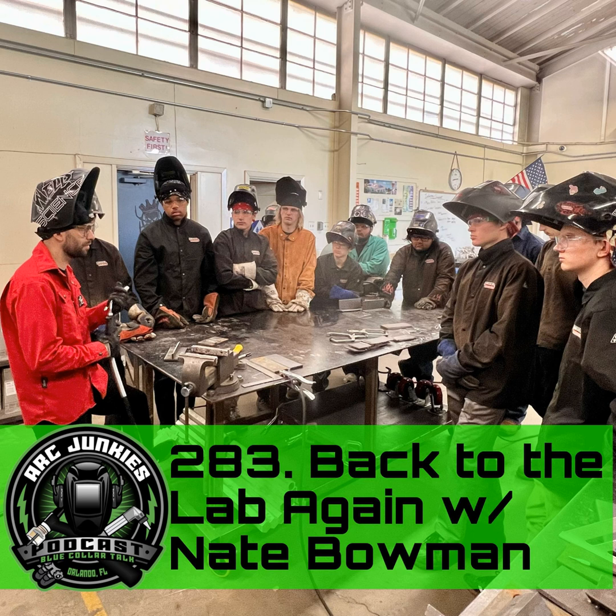But the problem with welding in AC is you don't get as much penetration as you do with DC reverse polarity. But if I can control the amperage and the balance of my waveform, I can still get the penetration and I can still get the fill without having to worry about arc blow. Right. And you can kind of pick and choose. You can lean more on that DC electrode positive side for that penetration, or let's say you're welding on something thinner, you can lean more on that DC electrode negative side.